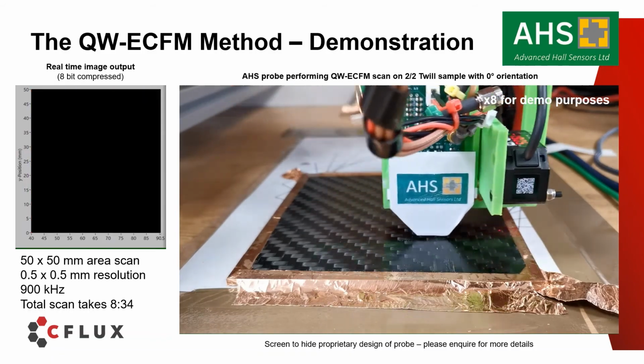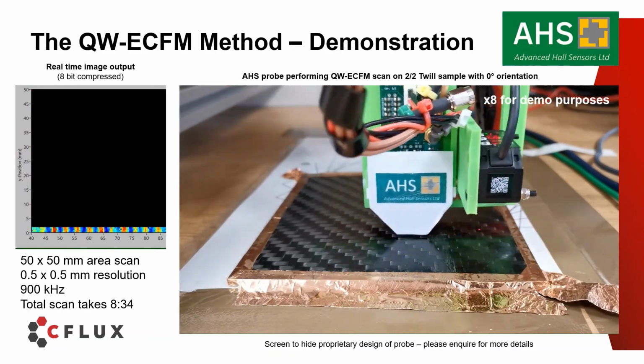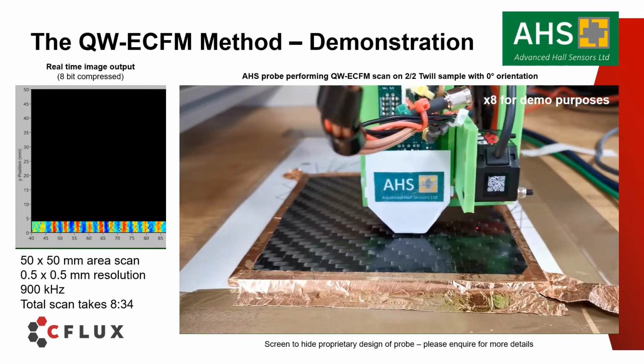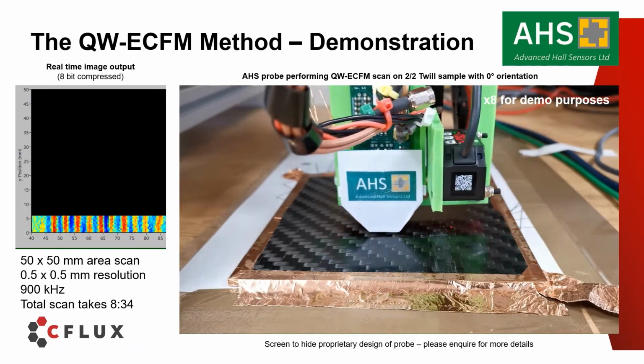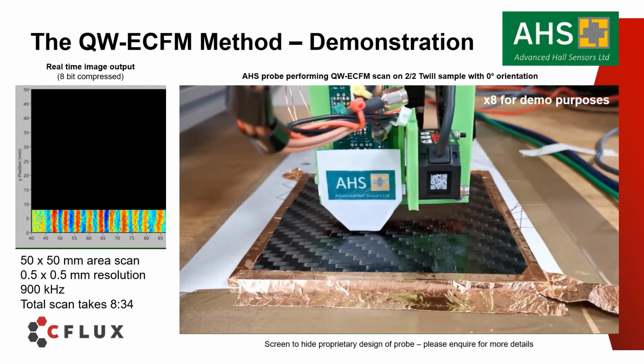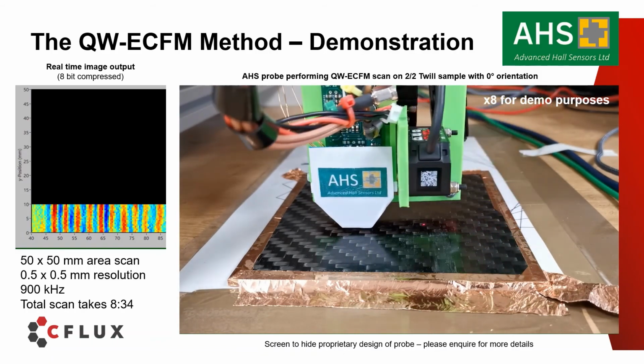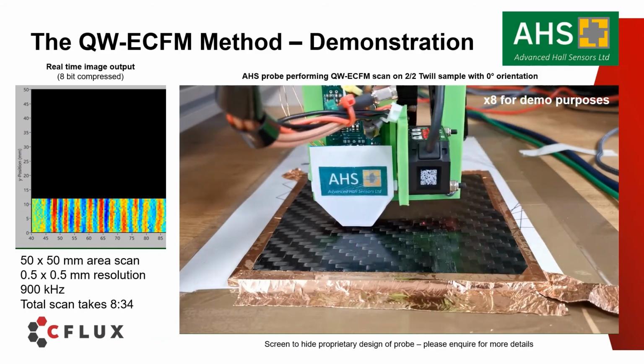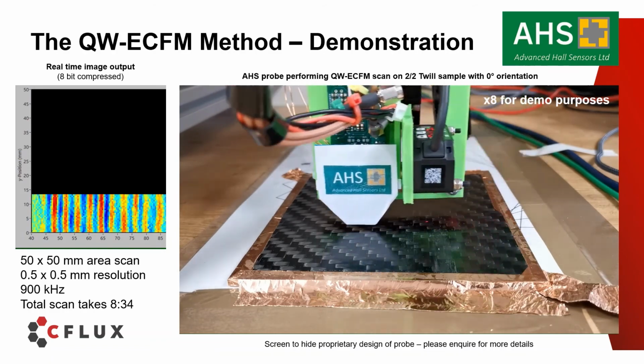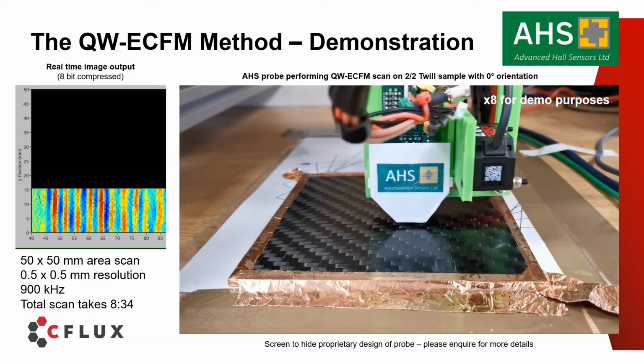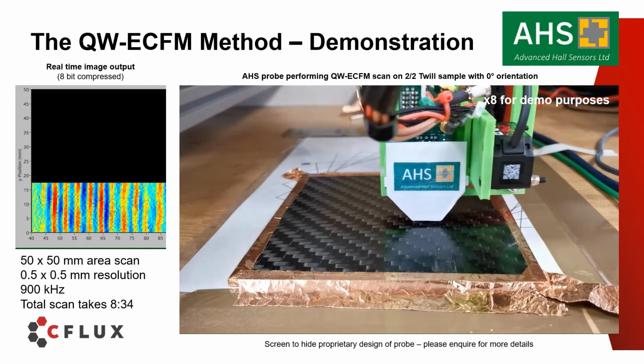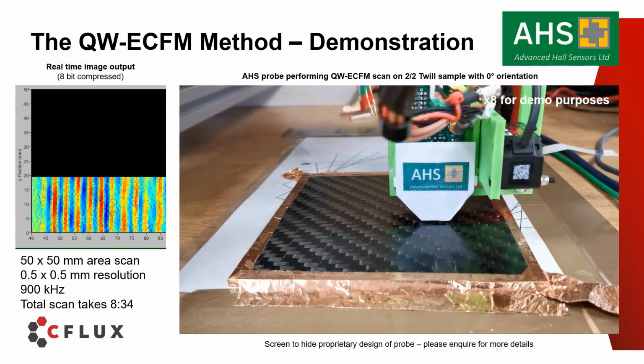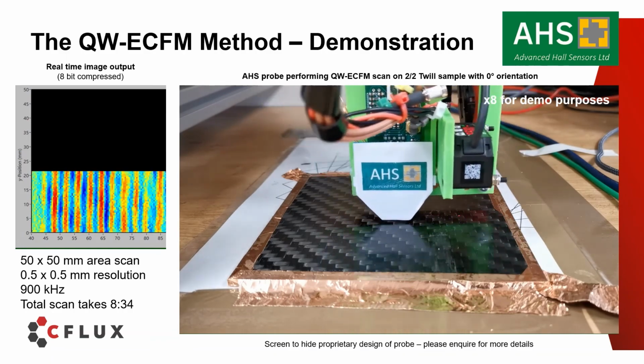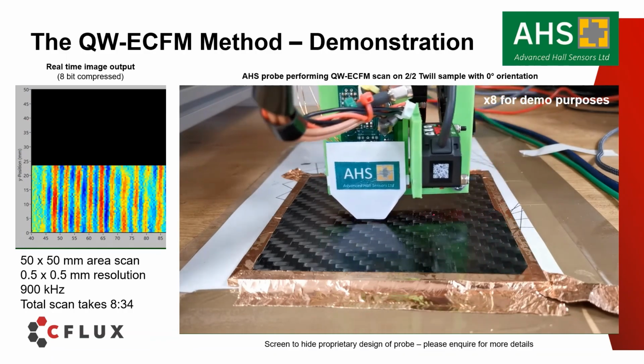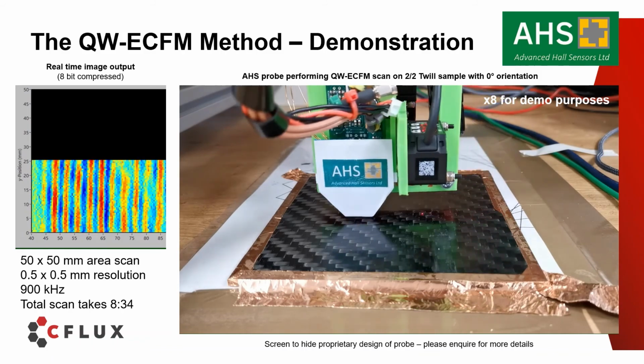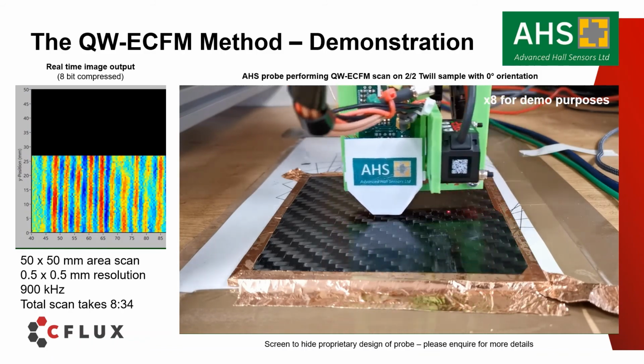The image appears grainy due to an 8-bit compression inherent to LabVIEW, which was used to control the scanner and generate the images. However, as you saw previously, the raw data from the scans can be compiled separately to produce significantly better quality images. The scan being performed is of a 50 by 50 mm area at 0.5 by 0.5 mm resolution at a frequency of 900 kHz. Due to the limitations of the scanner mechanism, the scan takes 8 minutes 34 seconds to complete. However, you will see that with a better manipulation system, this coverage time can be reduced significantly.